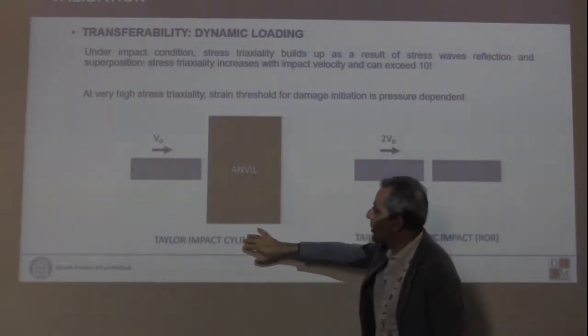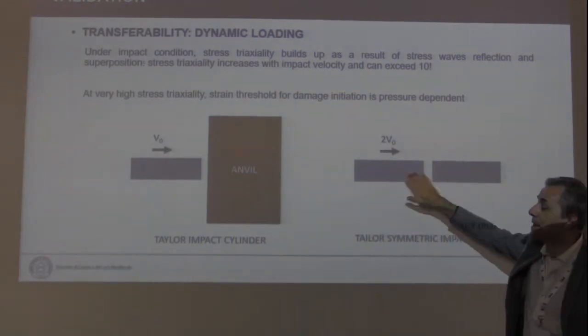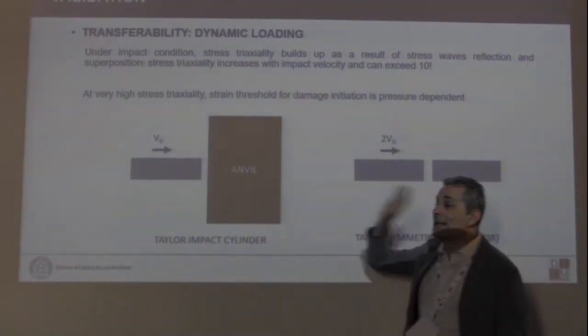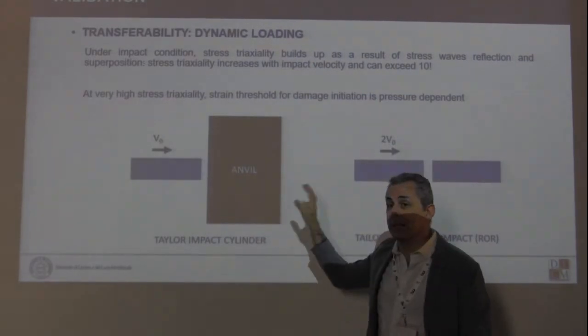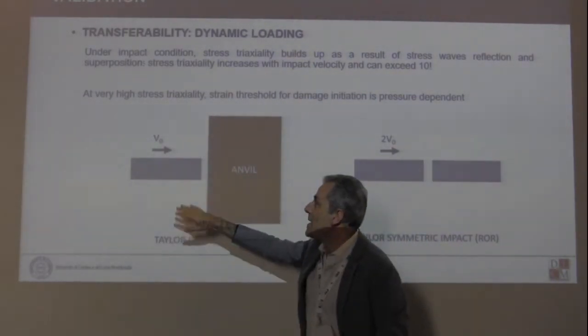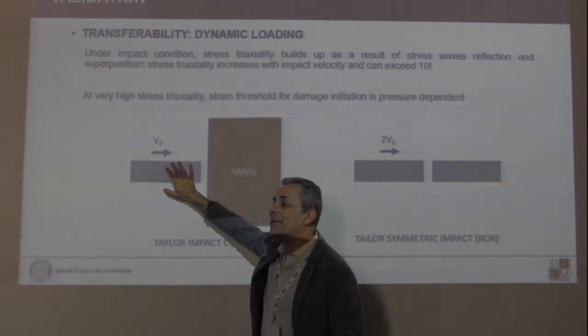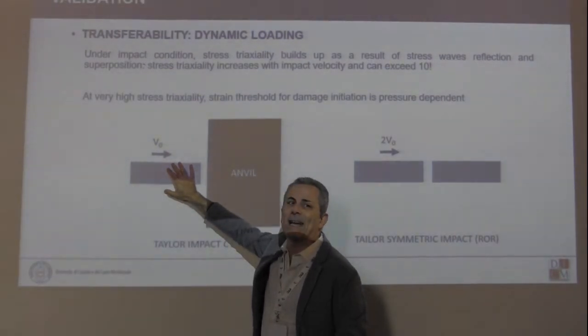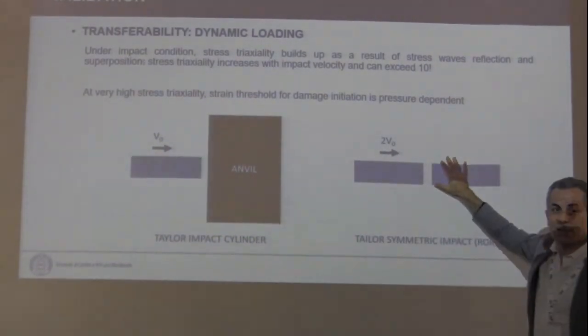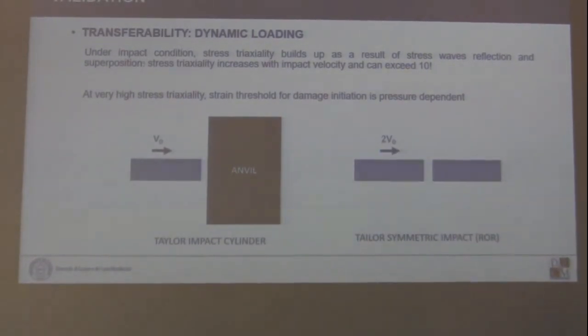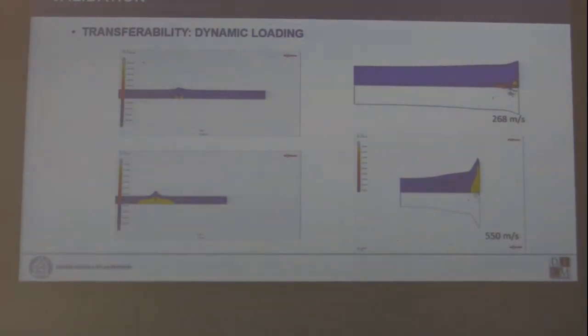which is called the Taylor impact test, or rod-on-rod test, where you have a cylinder impacting another cylinder. For the same material, for equivalent velocity, if you do this test, for a ductile material, you will never get damage. But you get damage in this case. So a model has to discriminate the two tests. We demonstrated that our modeling of continuum damage mechanics was capable to separate the two effects.